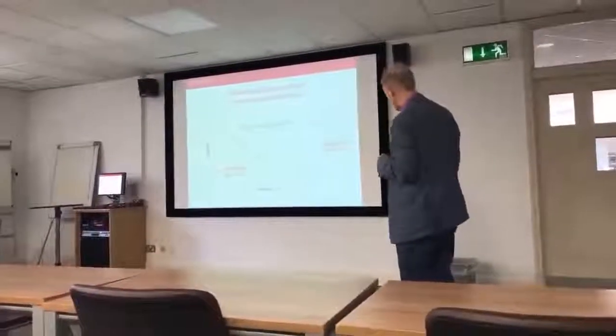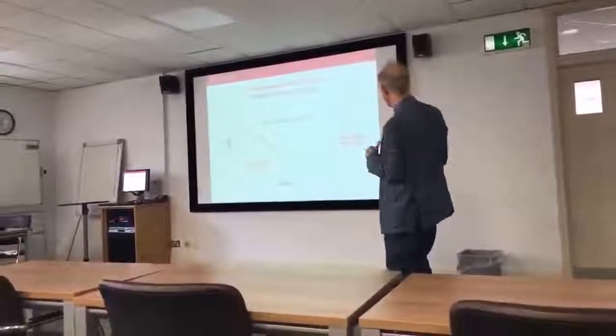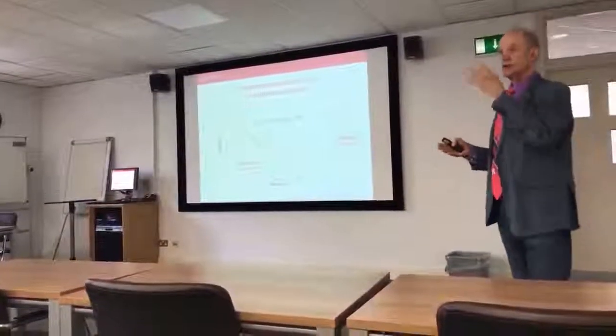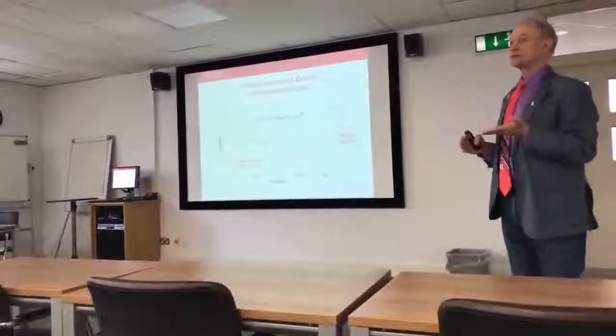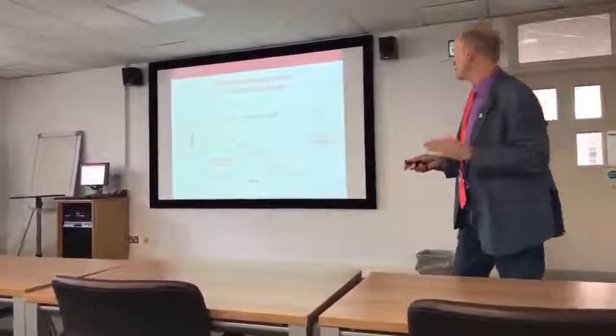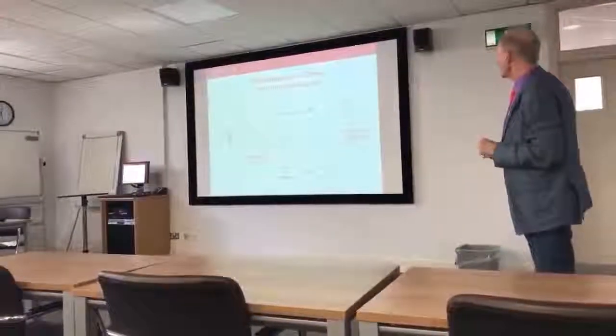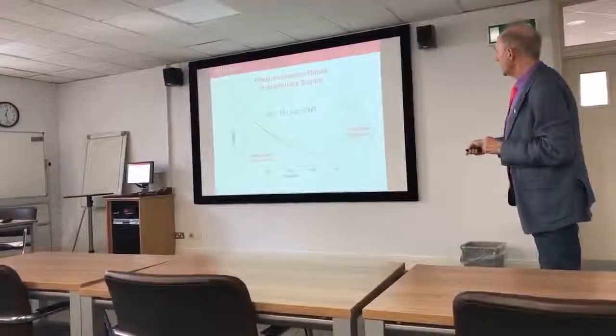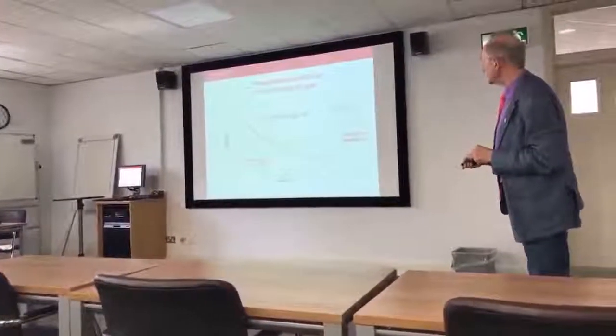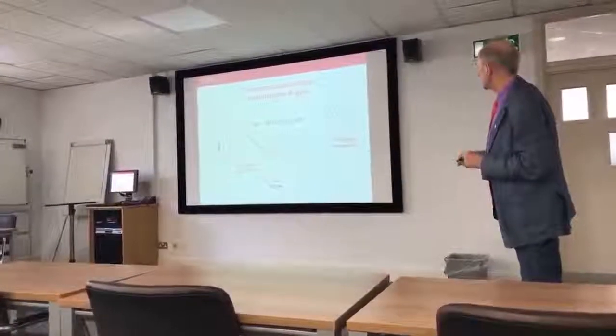Okay, so what we've done in this experiment is we take riboflavin at about 1 part in 10,000. We mix it with a sugar and water. We spread it on a quartz slide. We dry it extensively, as dry as we can, and we make it an amorphous sugar. And then we measure the phosphorescence decay, and this is for riboflavin at 20 degrees in maltotetraose, and you see the decay is occurring on sort of the millisecond time scale.